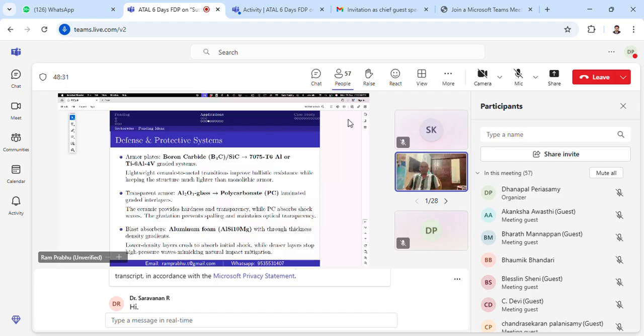In all these scenarios, the logic is very simple. You should have a hard casing and a tough core. The hard casing is usually from ceramics like boron carbide, silicon carbide, or aluminum oxide if you want transparency. And the soft or tough core is either aluminum because of its light weight, or titanium. So 7075 is a high strength aluminum alloy. Ti64 is another high strength titanium alloy, or a polymer like polycarbonate.